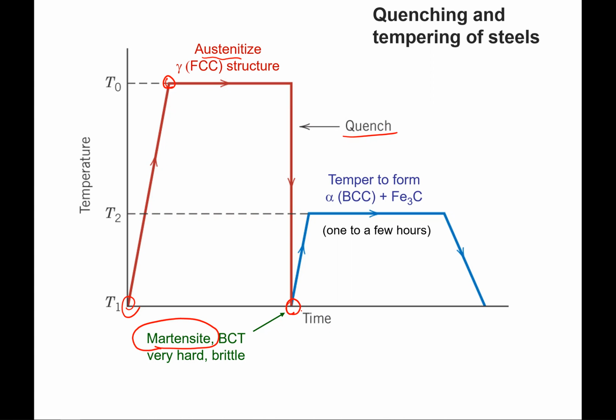So then what we're going to do is reheat that for just a few hours, maybe just an hour, a few hours, maybe up at 300, 400, 500 degrees C. And we're going to heat it, we're going to hold, and while we're holding, since we are, from the phase diagram, going in that ferrite cementite phase region, we now have enough diffusion, since we've increased the temperature, that the martensite no longer will be frozen in, but will actually form the ferrite and cementite from our equilibrium diagram. And so we're now going to get ferrite and cementite to form, and then we'll cool back down to room temperature.